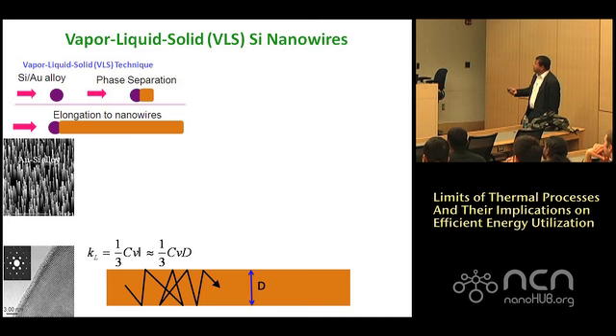And then the question is, can we break off some of these nanowires, put it on our device and measure? And the idea is that we can control the diameter of this by controlling the size. And if this diameter is smaller than the mean free path, then these phonons would bounce off the boundaries, and instead of the mean free path being controlled by phonon-phonon scattering, the diameter would control the mean free path, and you get 1/3 CvD. So as your D goes down, your thermal conductivity goes down. This is a fairly well-known approach. The question, does it work? It certainly does work.